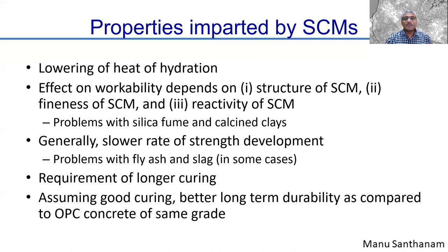So what are the properties that we are looking for as far as the use of SCMs is concerned? Sometimes we want to lower the heat of hydration. For instance, when we are doing mass concrete structures, we want to keep the heat of hydration as low as possible. Instead of going for special cements that are difficult to manufacture, what you can simply do is reduce the content of cement by using supplementary material.